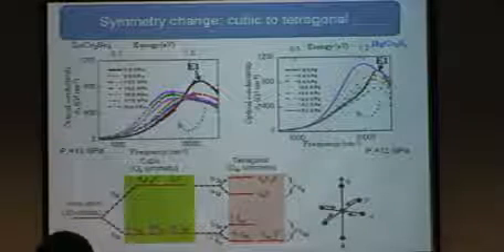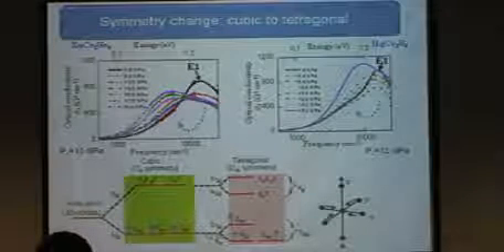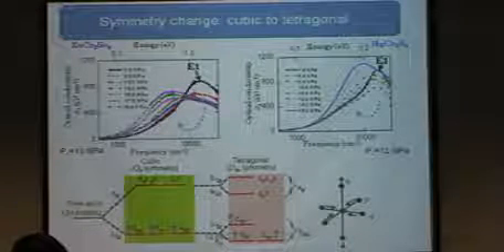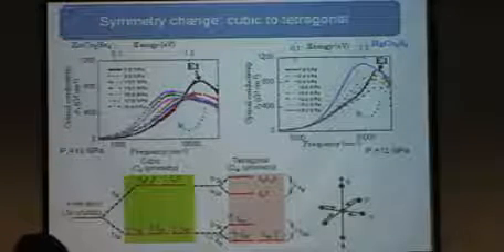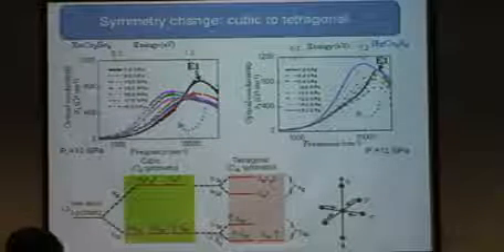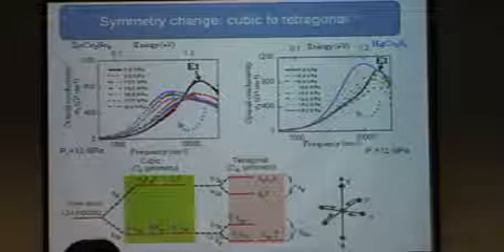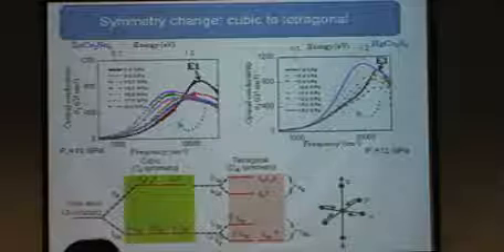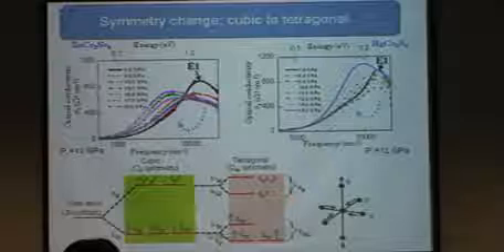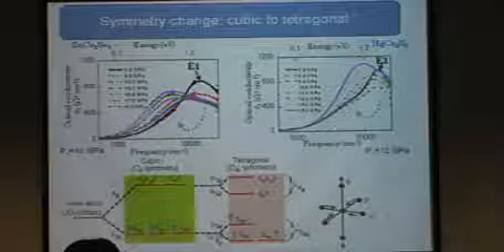And there was another point. If you see the spectral change towards low frequency, one can also argue that it could be the delocalization of the charged particles. But then in that case, one could observe this Drude term at lower frequency, meaning you can't see any shift in the reflectivity level. So that's why this delocalization of the charges is somehow not the explanation.